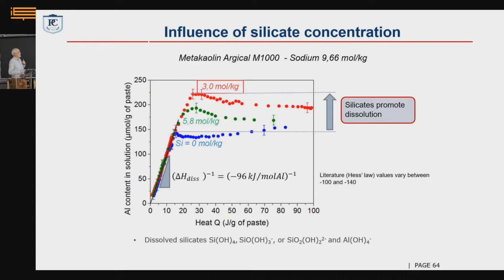Now I keep the amount of metakaolinite constant, I keep the alkalinity constant, and I just change the modulus by varying the concentration of silicate ions, by dissolving more or less silica in the sodium hydroxide, basically. So again, at the beginning, pure dissolution. But what's interesting is that if you have no silicon, no silicate ions, you dissolve your metakaolinite, and that's it. And when you put more silicate, you see that you change the behavior of the system. You go to a higher level. The alkalinity is the same. You have the same amount of hydroxide in solution at the beginning. But still, the fact that there are silicates impacts the chemistry in terms of the polycondensation and how far the dissolution goes before polycondensation starts to really dominate the system, i.e. the geopolymerization or the formation of the NASH gel, okay?